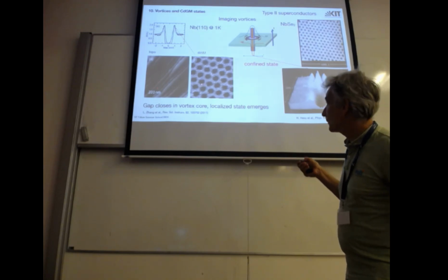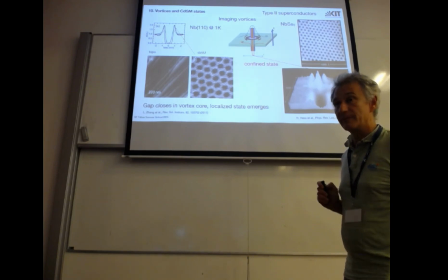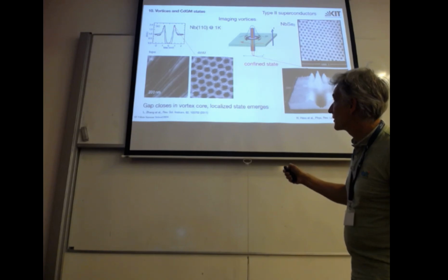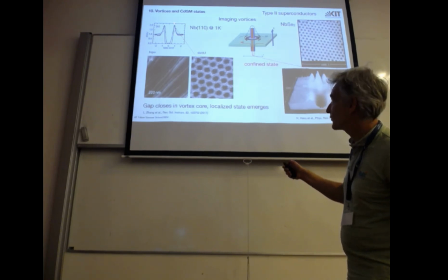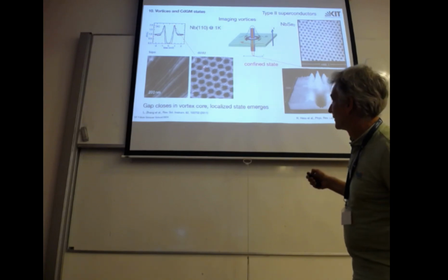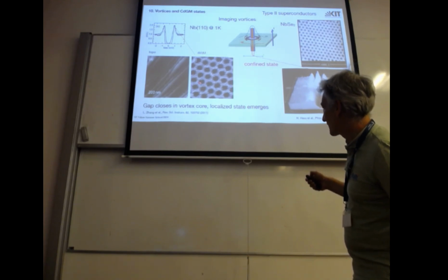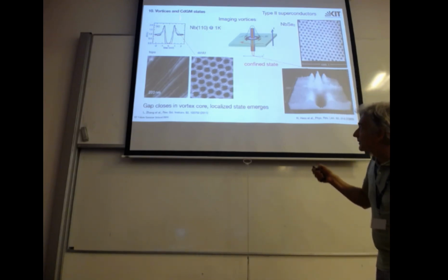At the same time, we modulate the voltage a little bit and measure with the lock-in dI/dV, and we sit with the voltage here. If we are on a superconducting part, you see the slopes, the differential conductivity is high. If we are on a normal part, then the dI/dV is normalized to 1. So normal is 1, superconducting is under these conditions 2. 2 is larger than 1, so it appears bright in this image. We just map this quasi-particle.